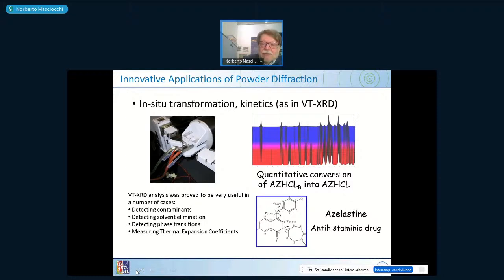You can detect phase transitions, solid-to-solid phase transitions, polymorphic phase transitions, which are not seen if you dissolve them into solution to obtain a normal chemical analysis. And you can also measure the thermal expansion coefficient down to very tiny values, 10 to the minus 5 coefficients.